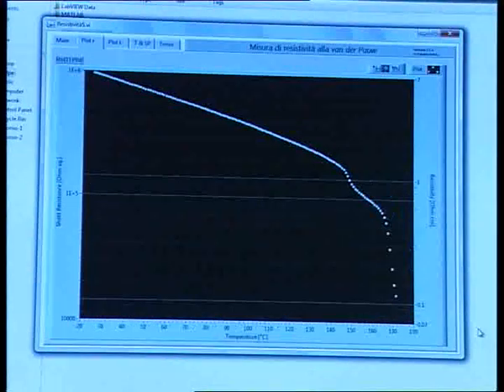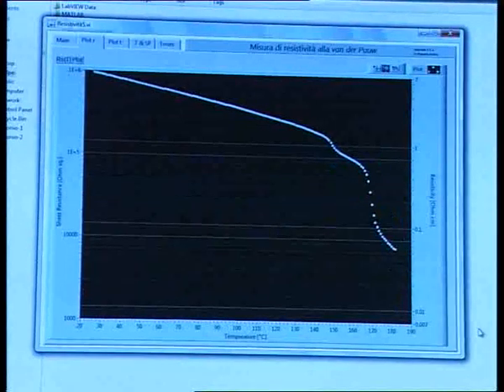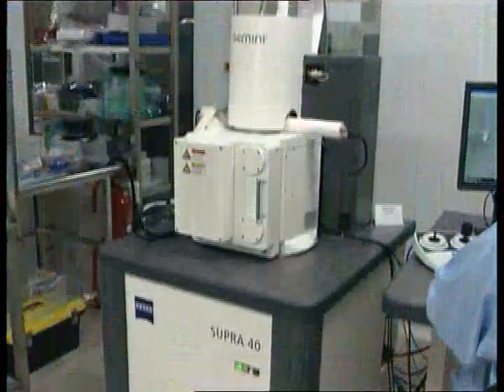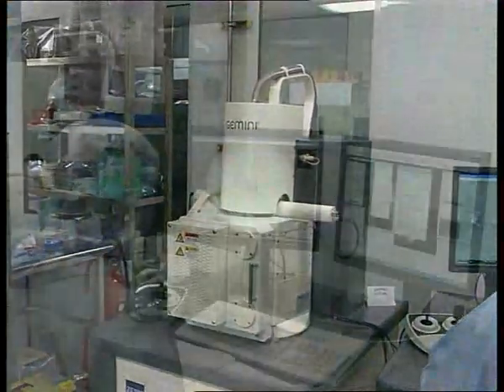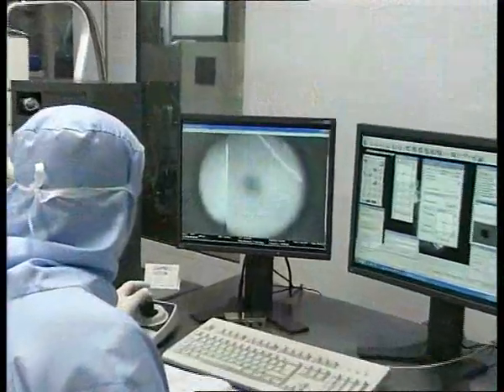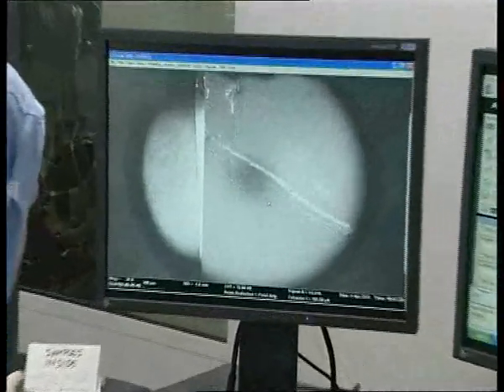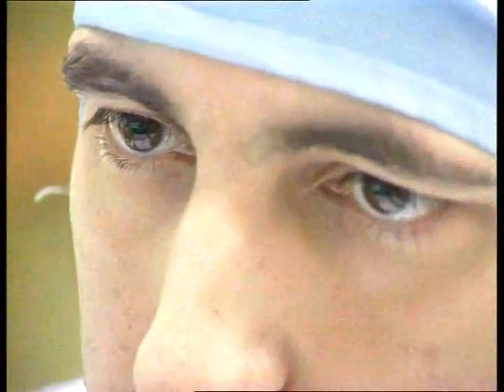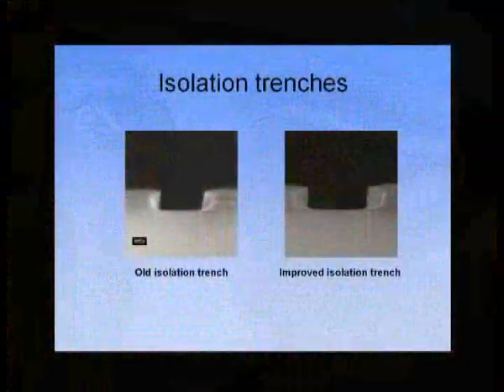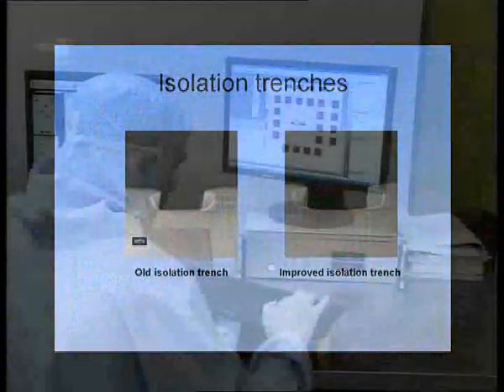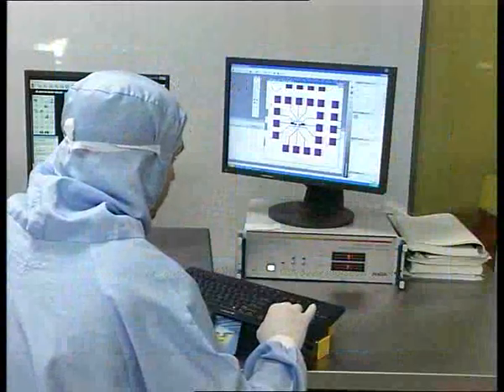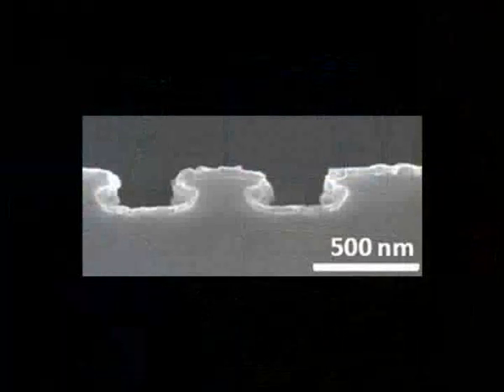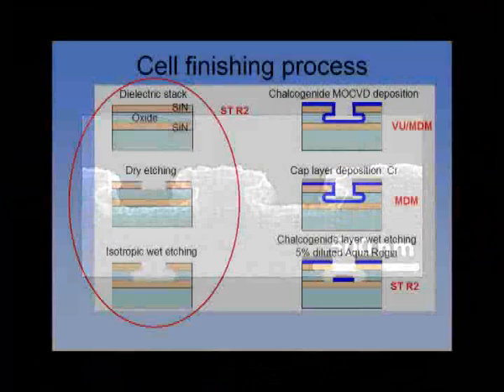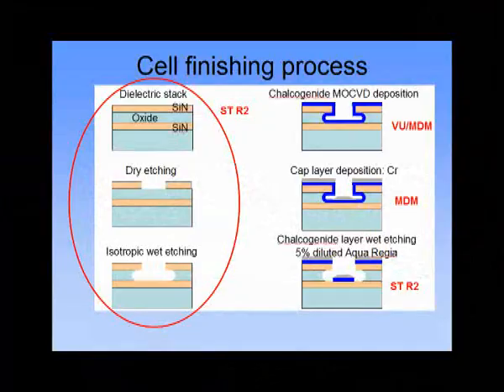The best results in terms of device performances were obtained with GST deposited by hot wire chemical vapor deposition at Vilnius University. In the pure spirit of a European collaboration, the cells were first prepared in Italy by ST Microelectronics, sent to the University of Vilnius for chalcogenide deposition, sent back to MDM for device finishing, and finally moved to ST Microelectronics for device testing.